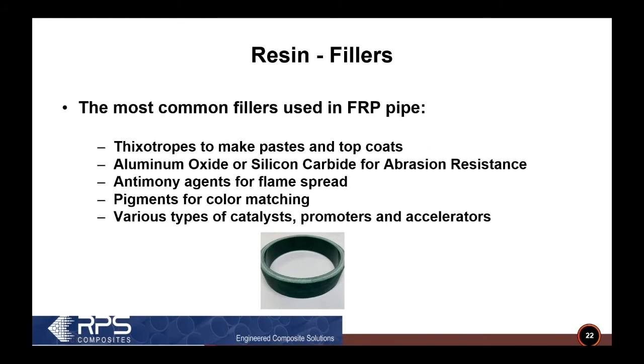And once you've got the resin, then you've got to figure out, do I have to add something to the resin? Typically, we add things called thixotropes to make the resin thicker. We sometimes add aluminum oxide or silicon carbide to make the resin abrasion resistant. We can add antimony agents combined with the resin manufacturer, adding bromine to make the resin have a lower flame spread. Of course, we can pigment the resin like you see in the picture. And then we're going to add different things to catalyze and promote and accelerate the resin. That's going to affect the gel time and the working time you have with the resin.